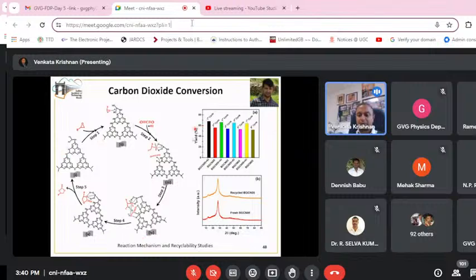We also did the recyclability study with and without the potassium iodide, which is indicated here, because potassium iodide is soluble in water. When we recover the catalyst, after recovery we wash it multiple times with water to remove anything sticking onto the catalyst.